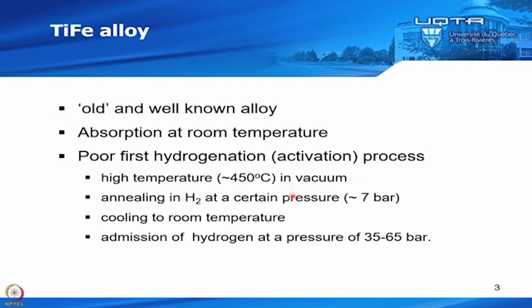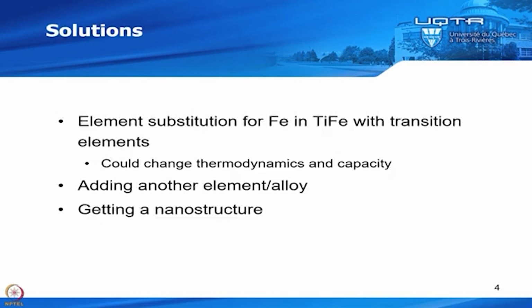in vacuum. After that, you anneal at a certain pressure, like 7 bar. You cool to room temperature, and then you go to high pressure, and you do that a couple of times. So it's a lengthy and complicated process. What would be ideal is to be able to do the activation, the first hydrogenation, directly at room temperature under low pressure. So how could you do that?